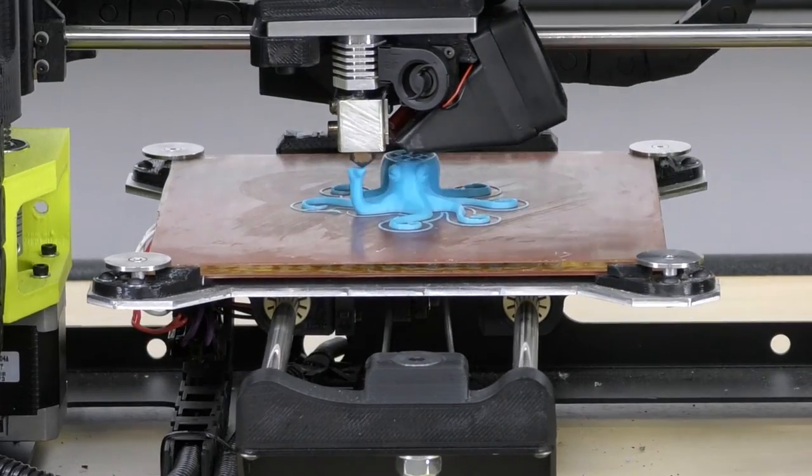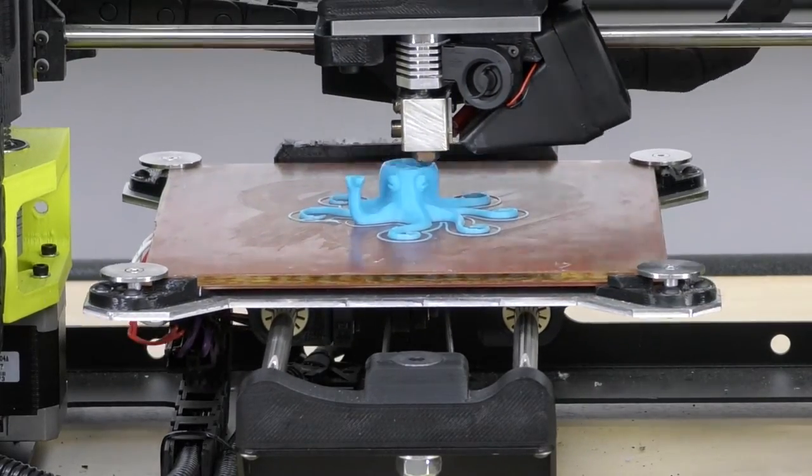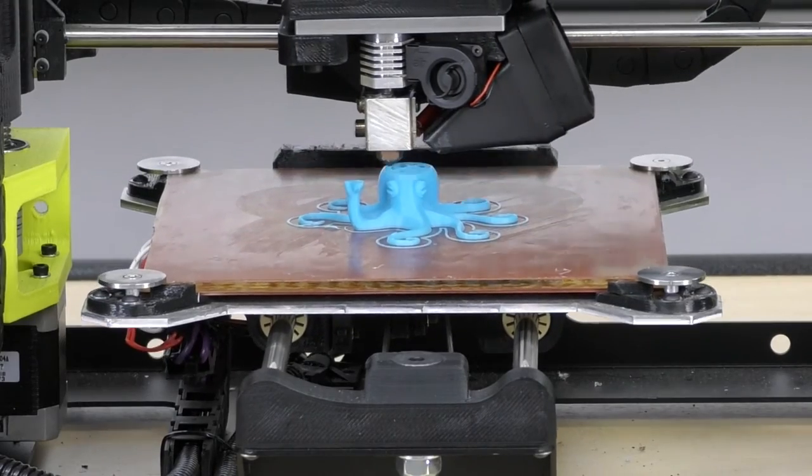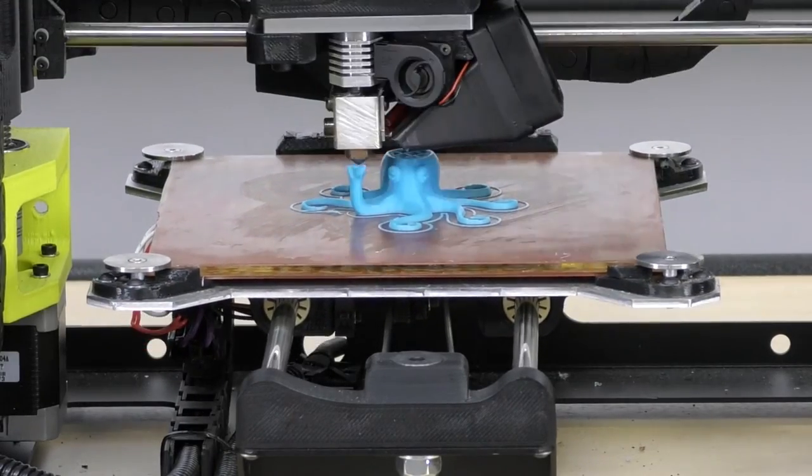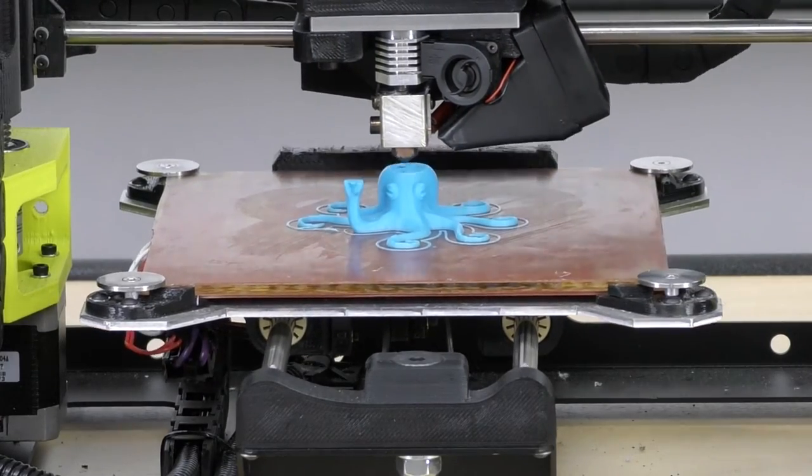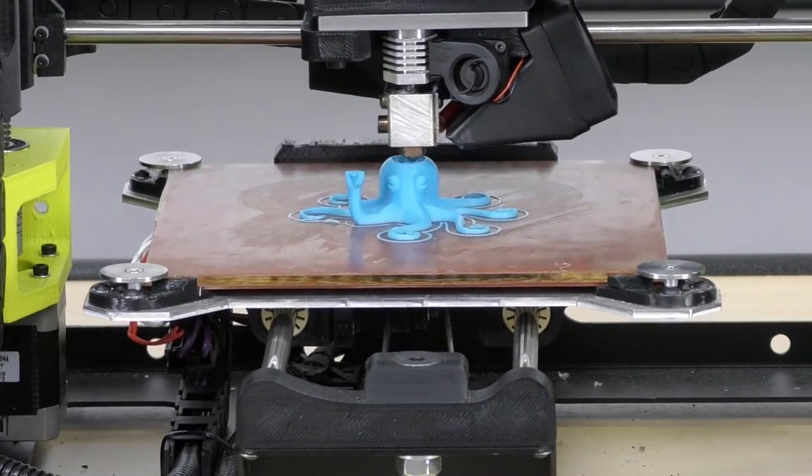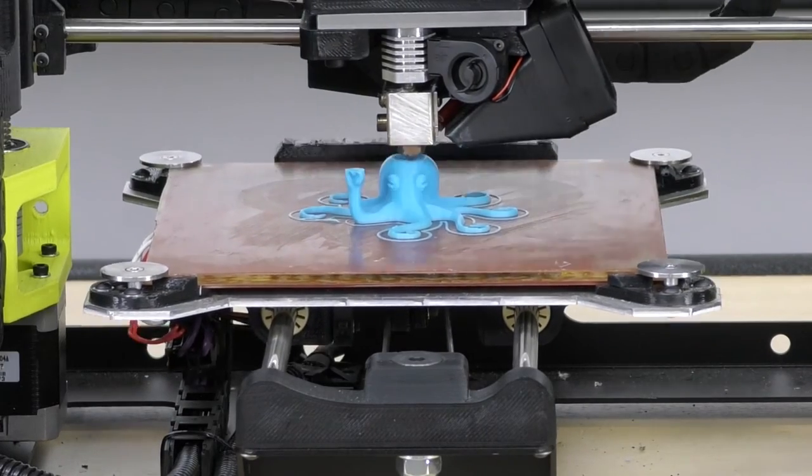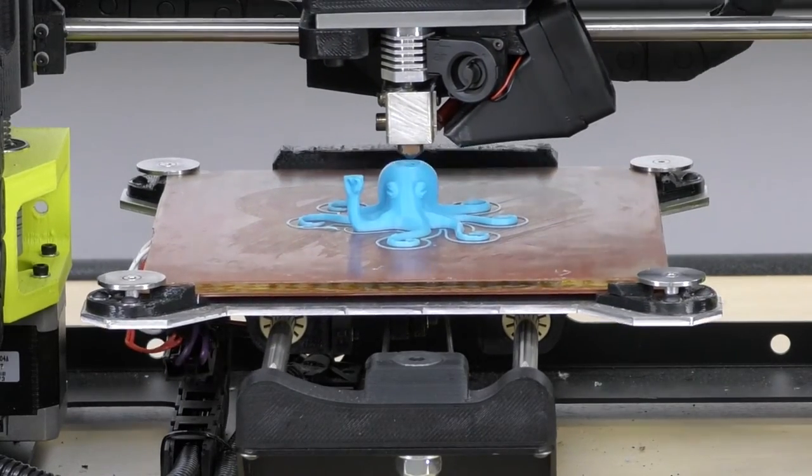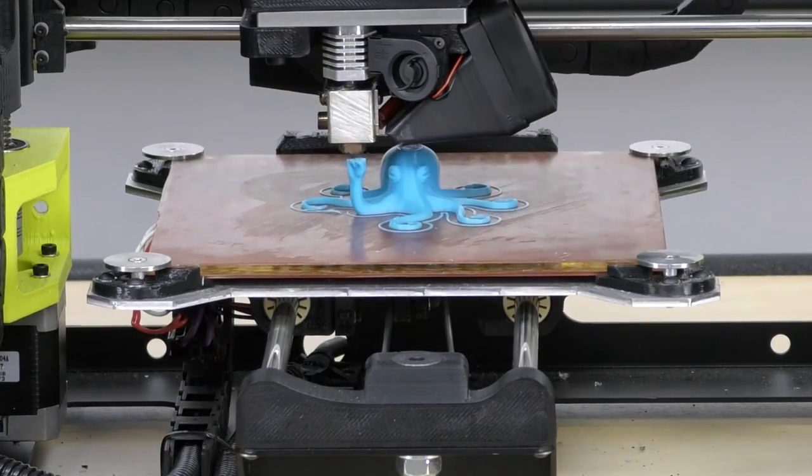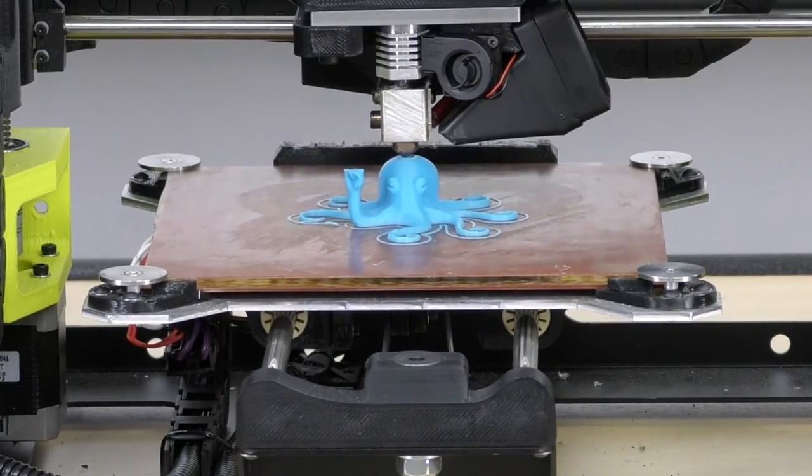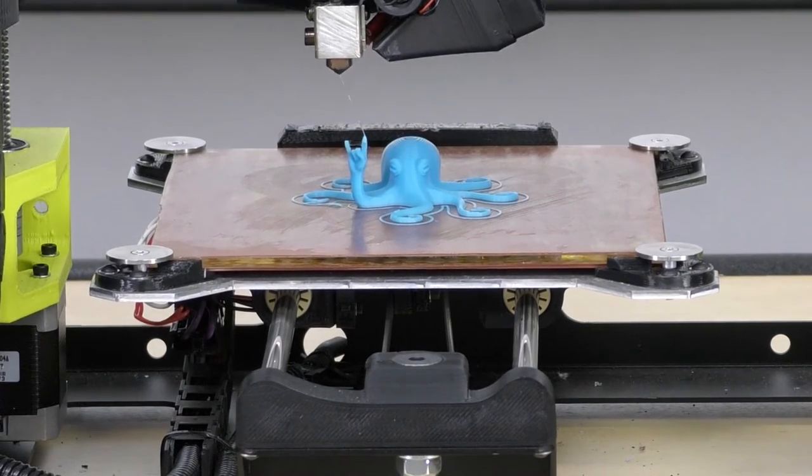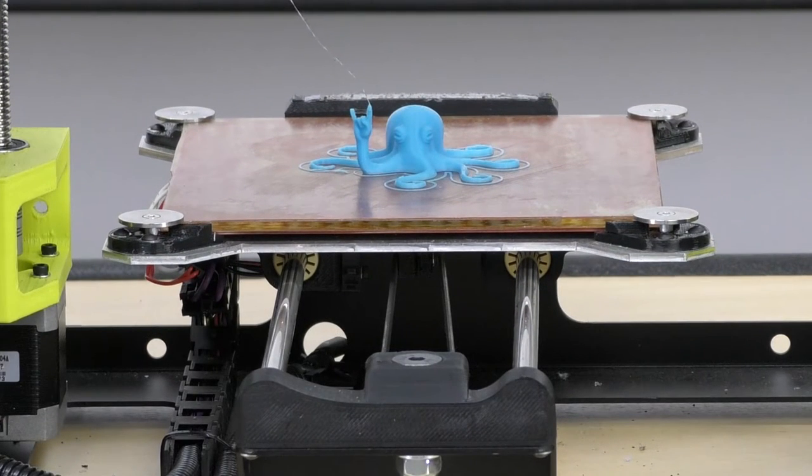Another great thing about these printers is this PEI sheet. Now, you can see that that first layer went down really easily. The printer just sort of, it knew where it was because of the auto-leveling system. And the PEI sheet's heated up to about 110 degrees. And because of that, we've just got that filament laying down nice and easily. It's going to hold it there. The whole print's just going to hold to that bed through the entirety of the whole print. And you'll see, at the end of the print, the print bed will move to the back. The PEI will cool down to about 60, 50 degrees, and then when it's ready, the print bed will move forward to the most forward position.